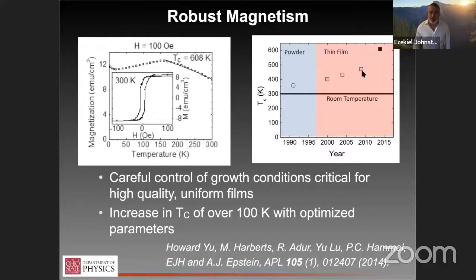So this is material grown by chemical vapor deposition, which evolved from an initial solution phase synthesis. You can see M versus T here is relatively flat, but it has quite nice hysteresis and sharp switching and saturation at low field. In addition, because it's a molecular-based system, the CVD is actually quite modest environmental conditions. So the pressure where we grow is a few torr rather than 10 to the minus 10 torr for a UHV system. And the temperatures are about 60 degrees Celsius. So this is actually magnetic spray paint effectively.